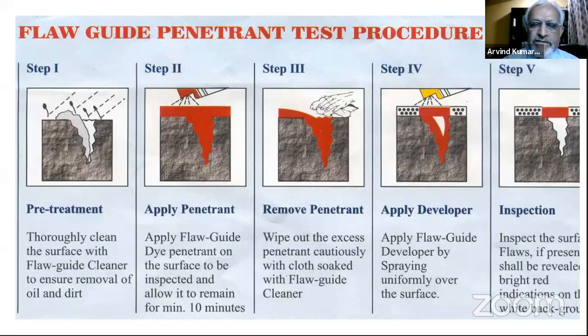And then once it has entered the entire cavity, we remove the excess penetrant. The next step is removal of the excess penetrant which is there on the surface of the test piece that you are conducting. It could be a weld or another surface. Again, this requires a bit of technique. Otherwise, if it's not done properly, there are chances you might remove the penetrant which has gone inside the material. If you do it rigorously and over a longer period than is required, then you will be removing all the penetrant which was there in the defect.